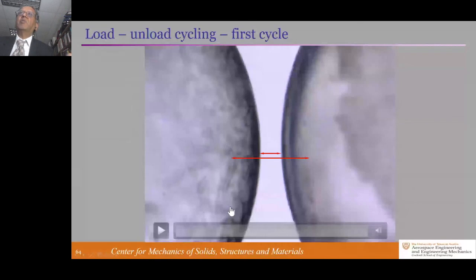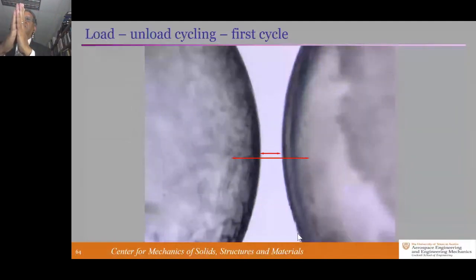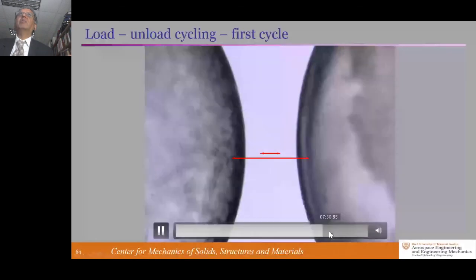The red line, small line, is the initial distance between the two. We stretch them. Somewhere about there, there's a cavity that pops from the right-hand side, and then we unload it. So now we're going to start unloading. We unload it back to the original place and hold it there. The black spot disappeared, which means the cavity has closed. If it is a cavity and you reload it, you expect that it would open up. So we reloaded, it hasn't opened up at all.